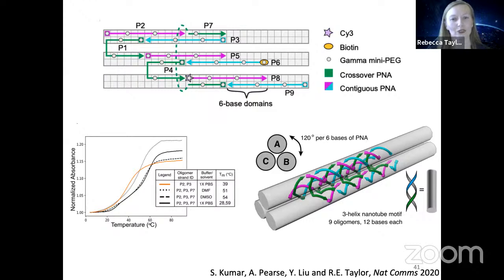And so there were huge geometric constraints, but we came up with a system that would create structures that were not largely pre-stressed. And so we made these 3 helix nanotubes. We showed that, you know how I said it binds more strongly to itself than DNA does? Well, we showed that the thermal stability of about 6 base interactions is better than like 10 or 11 bases of DNA. So we could get away with short sequences.